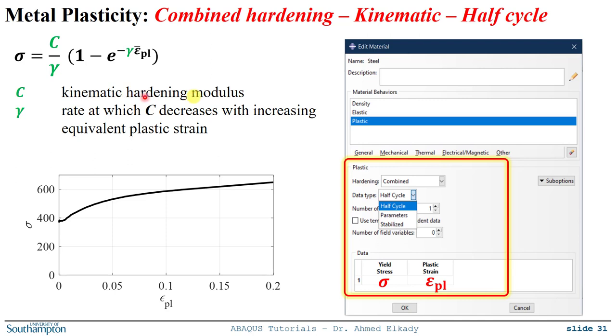C is called the kinematic hardening modulus, and gamma is the rate at which C decreases with increasing equivalent plastic strain. So the first option to define this is by inputting the data for a half cycle of a uniaxial tensile test, similar to the one that we did in the previous tutorial. You can insert the tabulated data for your yield stress and the plastic strain directly. This is the plastic branch of your true stress-strain behavior, and you can input the data directly over here. This is called the half cycle approach.